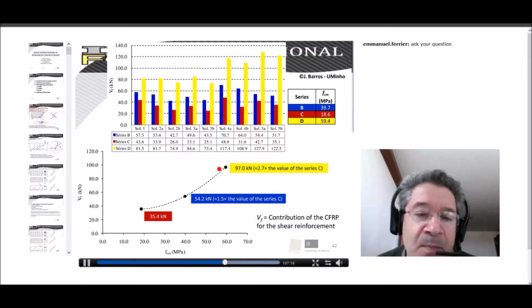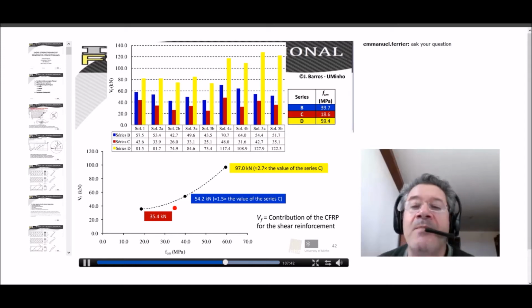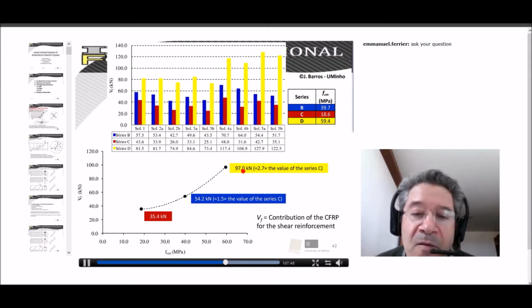For instance, using a concrete in the beams with an average concrete compressive strength of about 40 megapascal was 1.5 times higher than the contribution of the CFRP in the series with the average compressive strength about 19 megapascal. For the series of beams with the highest average compressive strength, that was about 60 megapascal, the effectiveness was about 2.7 times higher.